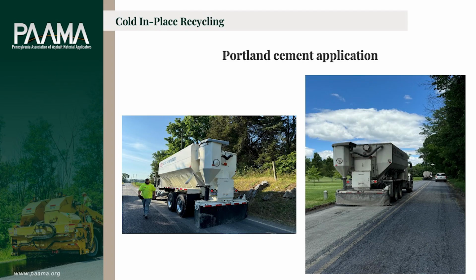So what the cement does is it chemically cures the road out. So within 3 days, that moisture's gone. That small amount of Portland cement has taken that out of the mix. It also makes it a stronger mix. So you could say that our recycle mix, at 4 inches compacted, has about a 0.4 structural coefficient.